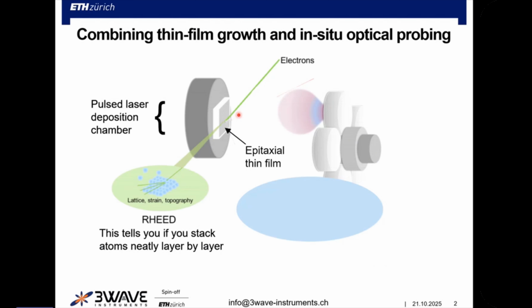So what we do is we combine thin film growth and in situ optical probing. Well, it's not the first tool that we would offer here. So we possibly all know RHEED. That with an electron gun, while you grow a thin film with pulsed laser deposition or even MBE, you see that you neatly put atomic layer on atomic layer by sending in an electron beam, and that sees neatly that your structure grows crystallographically as you want it.